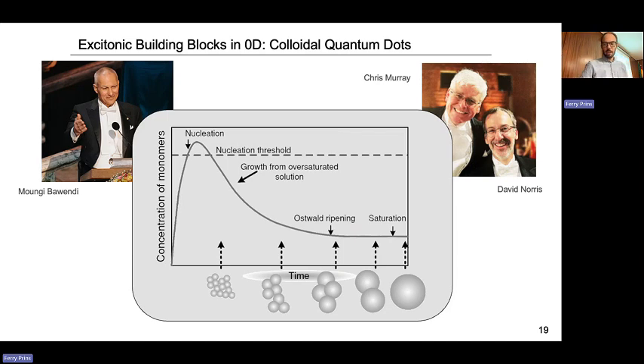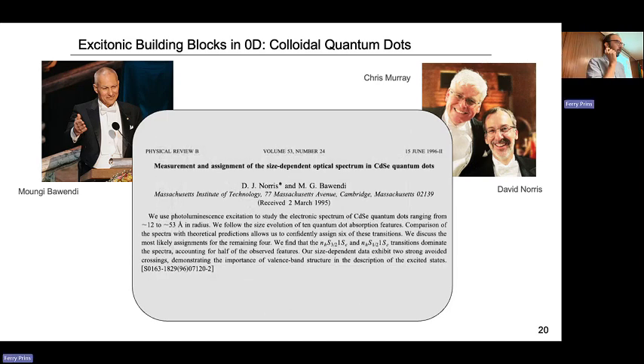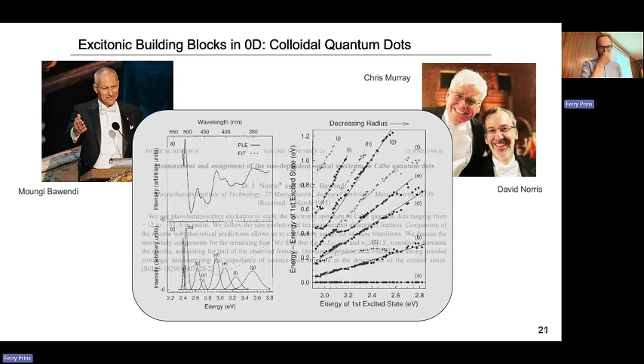And if you can control the size, then you can do physical chemistry. Because now you have a system where you have a perfect set of nanocrystals, where you can now start distinguishing all these different orbitals that we have created, because at the end they're just molecular orbitals. So this is a paper by David in '96, where it's measurement and assignment of the size-dependent optical spectrum of cadmium selenide quantum dots. And this is really beautiful.